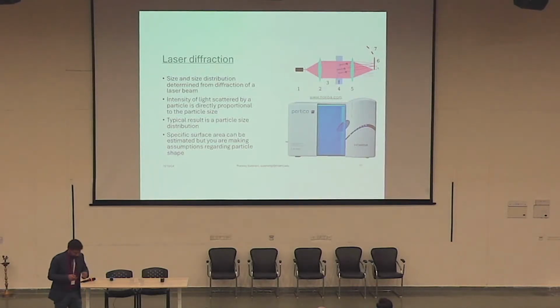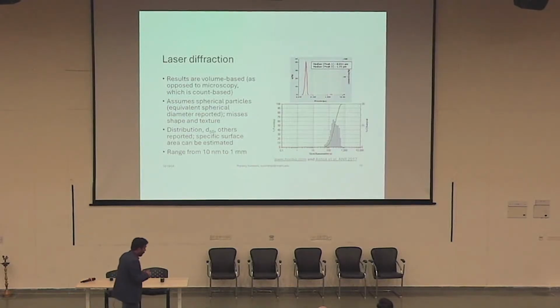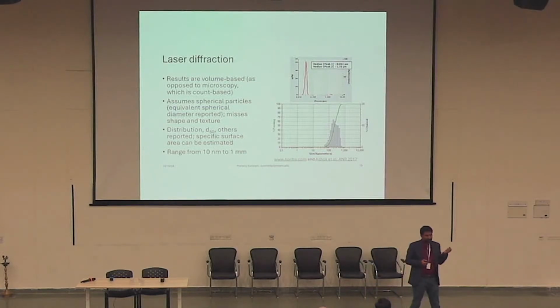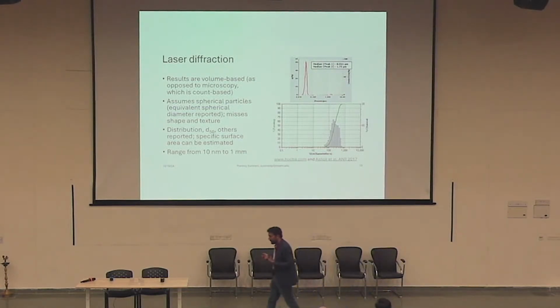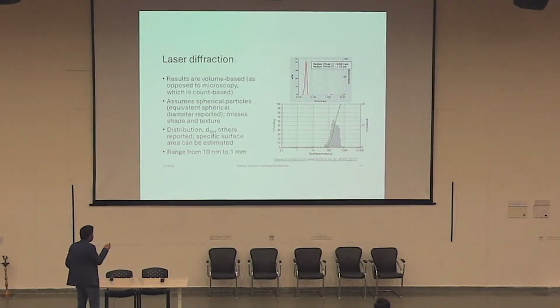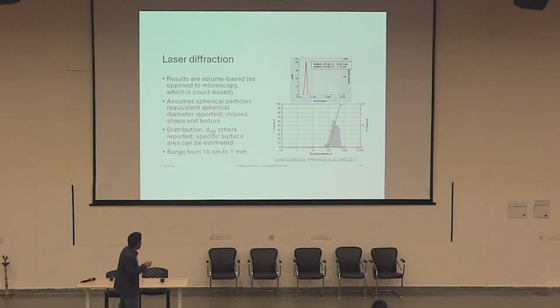Okay, a decent number. So when you're comparing different measurements, right, you need to know what you're measuring, meaning microscopy is count-based, laser diffraction is volume-based. So if you have particles with differential densities, right, then the results may not align. And of course, what this is telling you is an equivalent spherical diameter. It automatically assumes that all particles are spherical. So if you have a set of particles and some of them are less spherical than the others, you miss that complexity in this measurement.